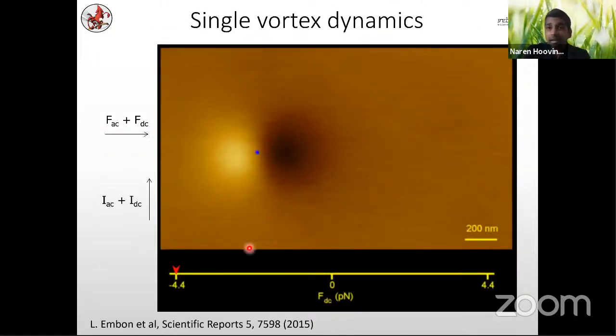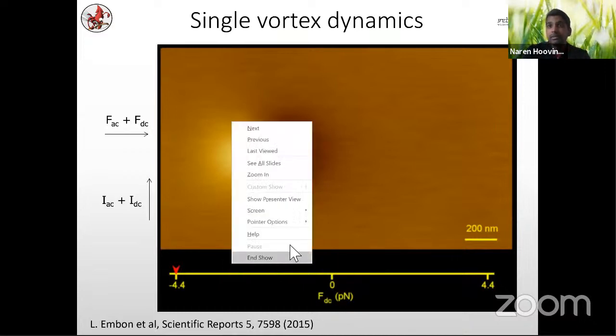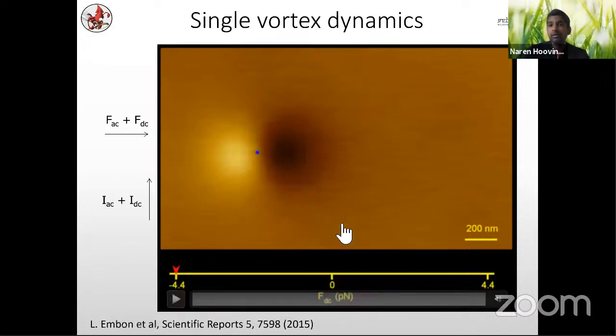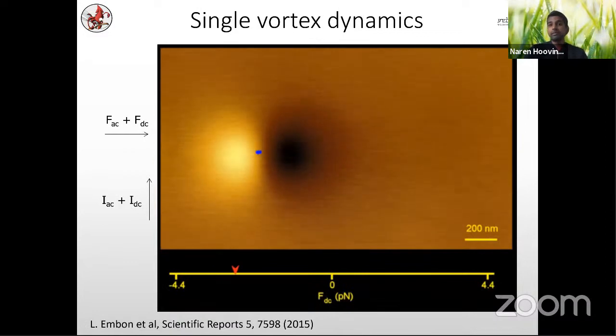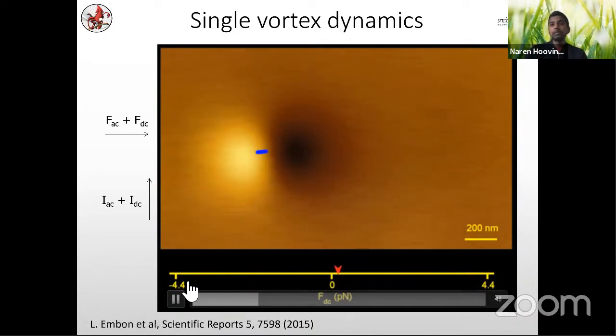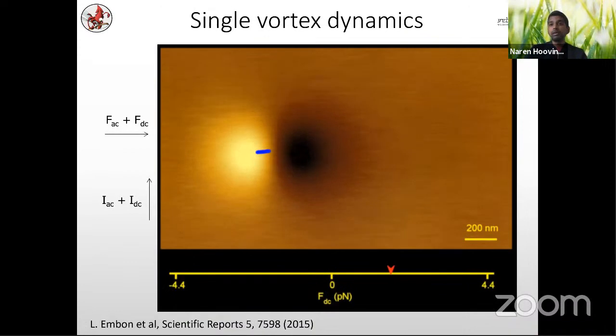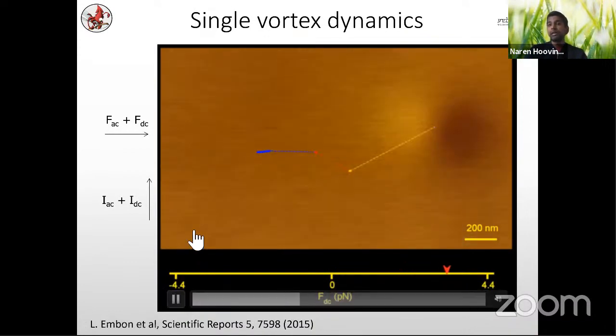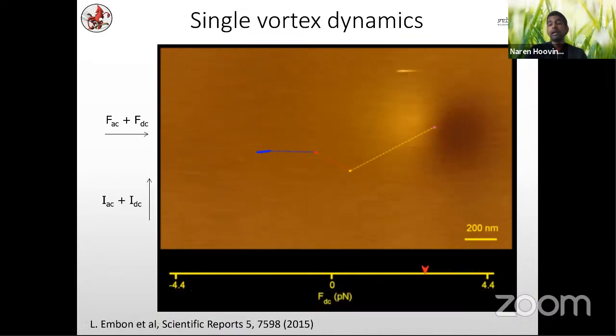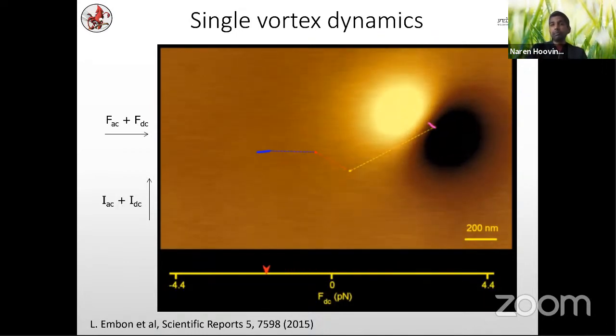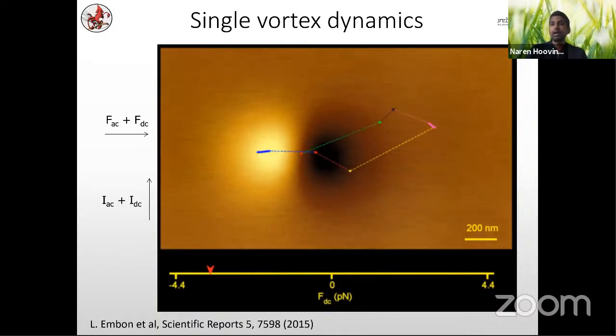So yeah, and then finally I'd like to show this video, which again shows how much can be done on the vortex state of this device. Basically, we can focus on one particular vortex and then vary the current, and then keep scanning the device, and when we put these images together, we can see that we can trace the trajectory of a single vortex. And this can then tell us more about the material, as to how hard the vortex gets pinned to a certain region, and how the pinning force changes with the current, and so on.